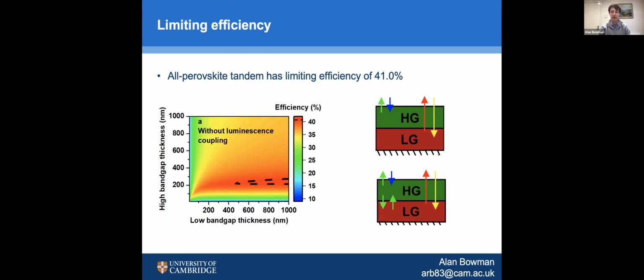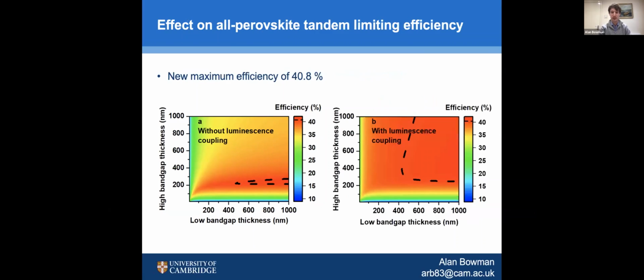And when we included that in simulations, we were really surprised because we came out with this graph on the right. And if you compare it to the left, you can see that suddenly you can make a very high efficiency halide perovskite tandem with a huge range of thicknesses. The slight downside is the limiting efficiency falls ever so slightly to 40.8%. But this right-hand side graph shows that it's much easier to make this kind of tandem than previously understood.